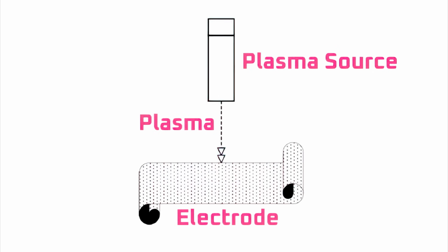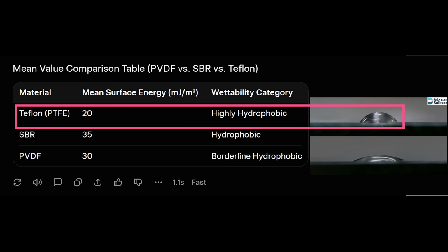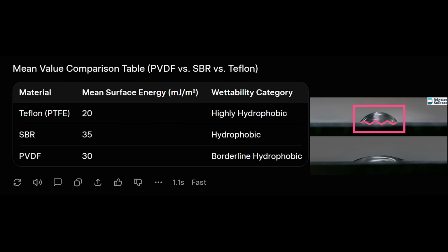How does the plasma treatment process work? As I said earlier, binder material, especially the PTFE binder that Tesla uses for their dry process, has a stable and non-interacting surface that makes it slippery and repellent to most liquids. In order to make the electrode more absorbent so that it can be saturated with electrolyte, and sticky so that it can adhere more strongly to the separator or current collector, the stable bonds in the PTFE on the surface of the current collector need to be disrupted or modified.